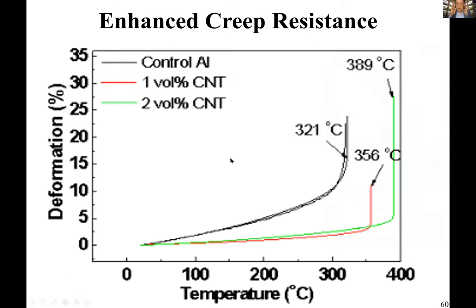So with all these effects, we show that, for example, with a 50% dead load, a control aluminum would have a creep rupture at 320 Celsius, but we can improve the creep temperature by 70 Celsius. And that's a big deal because aluminum is a very good material. It's corrosion resistant, it's light, but people know it's very soft at about 200 C also. So improving by 70 Celsius in creep strength is a pretty big deal.